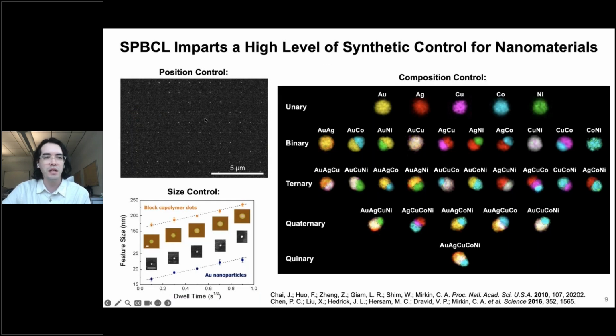And so with this SPBCL technique, what we have now is very precise position control of each of these nanoparticles. We can change the size of the nanoparticles pretty easily by just changing the volume of the reactors that we're using. And then we have very high composition control, because what we're putting into the nanoreactors will all end up in the final product. So in this figure we're showing up to 5 different elements that all then coalesce into single particles and get these very complex heterostructures that are very difficult to attain